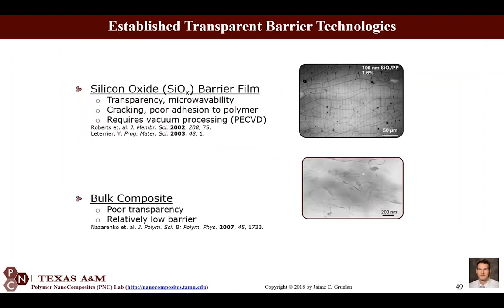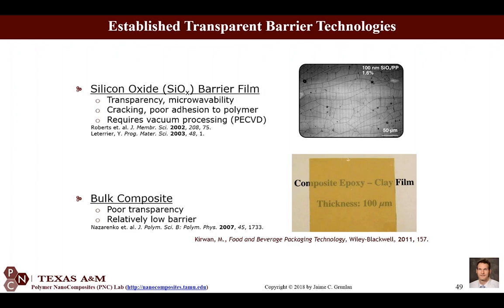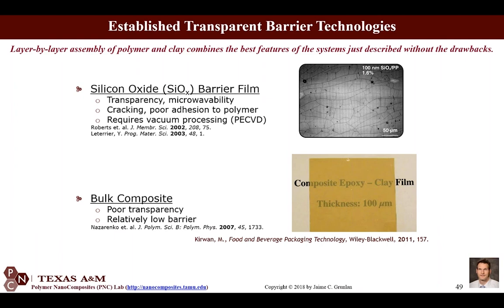The established technologies, especially when you're talking about transparent gas barriers, are usually metallized film or something like a silicon oxide that I'm showing here, or a bulk composite where somebody put clay or some other nanoparticle in to stop gas. One of the problems is you can get cracking in the silicon oxide. You can also get a lot of opacity because of aggregation in the bulk composite with that clay, as I'm showing here as well. So with layer by layer assembly, I always tell people I get all the benefits of these competitive technologies without their drawbacks. I don't suffer from these same issues.